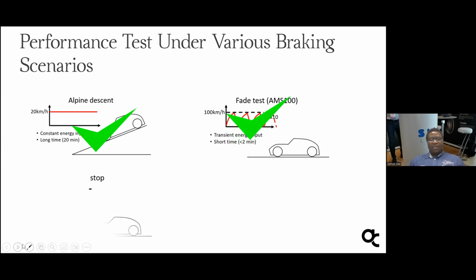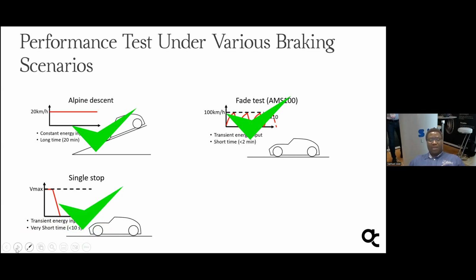Then another test is the single stop test. This one is driving at very high speed and you brake. This is used for emergency braking, which is very short, less than 10 seconds. So you drive at a very high speed, and you brake to 0. So a lot of energy is generated within the disc, and you can see like a fire. So the disc must cope with this kind of scenario, and this must also be passed.